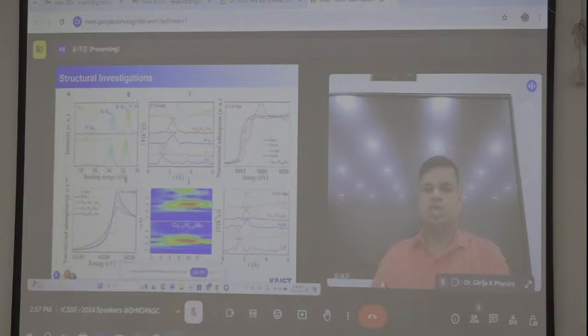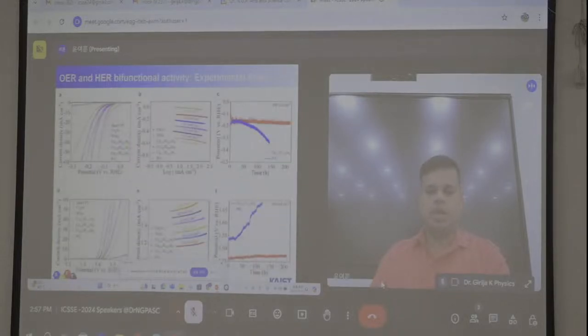And we also did structural investigations to prove the material, and did the HER, the kinetic studies and durability studies. And OER also we did, in both cases comparing with iridium oxide. You can see iridium oxide's stability is a very big issue, but in our case it is maybe highly stable.